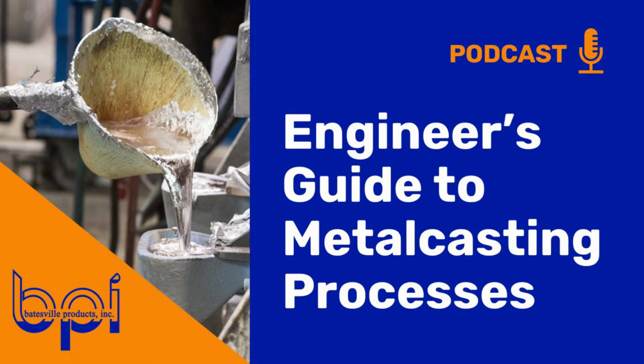But there are some automotive parts out there that are permanent mold cast, for example wheels and some types of transmission parts, because you can get that leak-proof characteristic from a permanent mold. Absolutely. If you were driving a car with die-cast wheels, you may not make it down the end of the road without the air leaking out, or you'd have to do quite a bit of sealing in the metal to get it to seal up. Die casting lead times tend to be a lot more drawn out than a permanent mold or a sand casting.